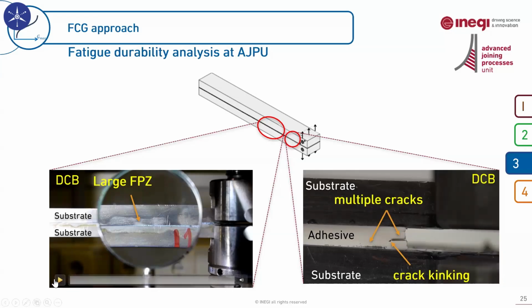We have here a very ductile adhesive with 150% elongation at failure. This is a methacrylate adhesive. And you see a very large whitening area. This is a magnifying glass. We try to zoom in a little more to see the very thin layer of adhesive here. The real size is here, hard to see the adhesive layer. But here you see that we have a crack, the crack tip is somewhere here, and these are the large whitening area and process zone ahead of the crack tip.